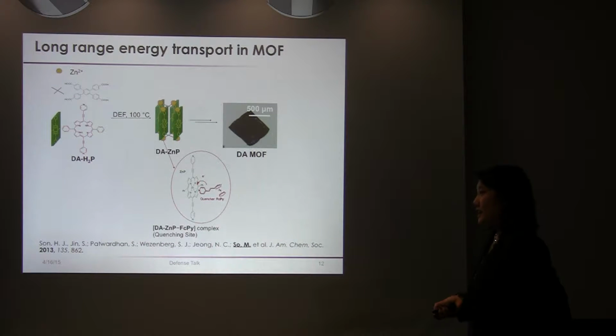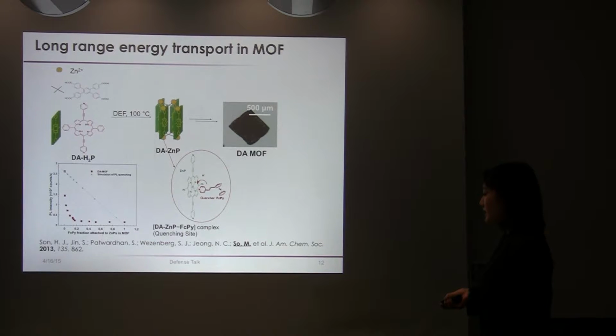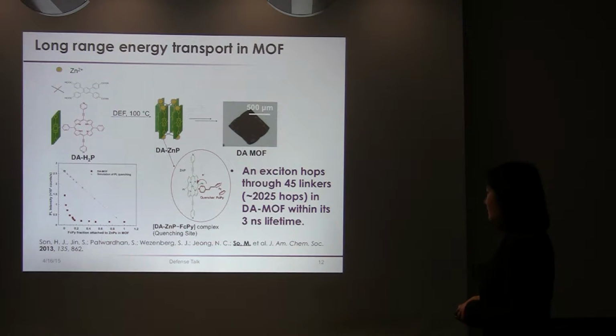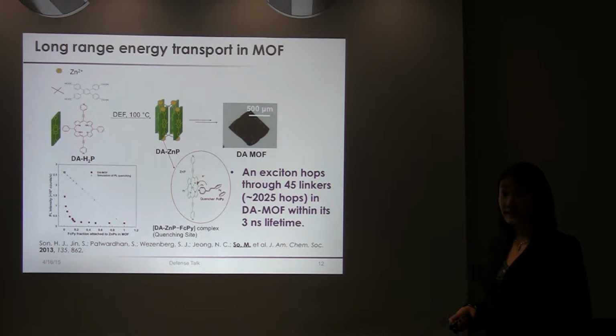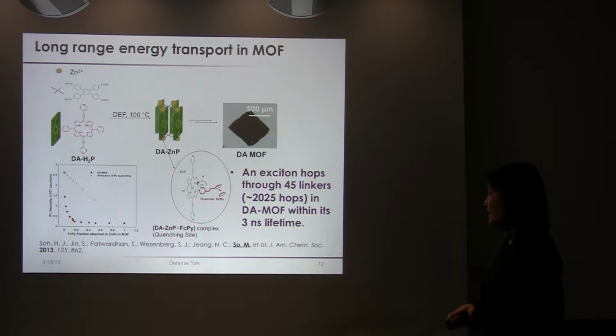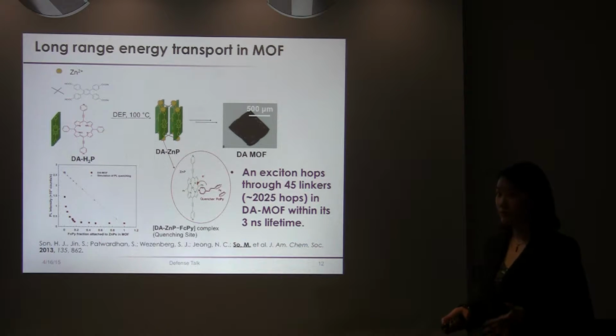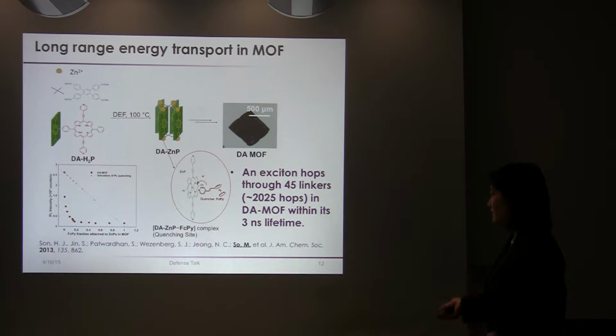Subsequently, we had doped the zinc metallated porphyrin with various concentrations of this quencher called ferrocenylpyridine. And based on the observed fluorescence quenching, we saw that the average number of distinct struts that are visited within the 3 nanosecond lifetime of the DA MOF was equivalent to about 45 of these linkers, which is equivalent to about 2025 hops. And this was very promising in terms of trying to extend the exciton diffusion length by a little bit more than 10 nanometers.